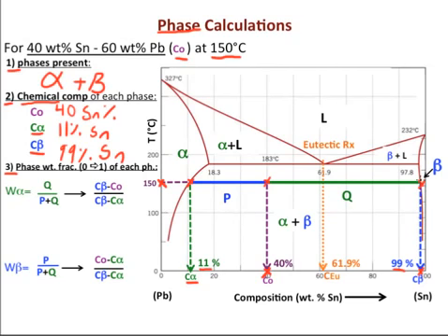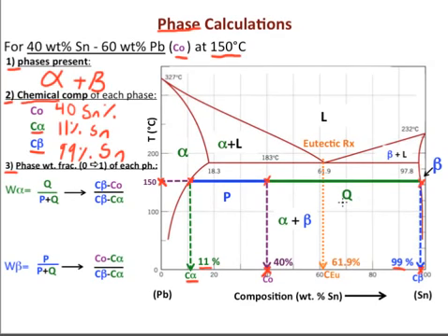And then we head from there to our nominal composition here, which in this diagram is labeled as Q. So for our weight fraction of alpha, we do Q over the entire thing, which would be P plus Q, so this entire distance. And this is what we call the lever rule, or the inverse lever rule. And if we start from over here, from 0% alpha, going this way, we can remember that this distance is the one that we use for alpha, and not this one.